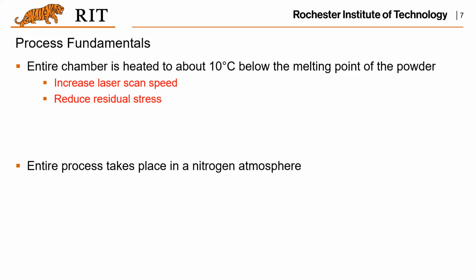Also, another requirement is a nitrogen atmosphere that will be filled in the chamber. The reason is that without such a nitrogen atmosphere, there could be some oxidation during this process for the nylon powder used in the process. So in order to reduce such oxidation, that requires the nitrogen atmosphere to be filled.